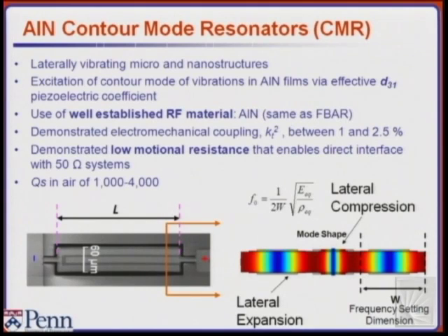And we solved one of the big problems generally associated with NEMS devices, which is the impedance matching. So we can design now a resonator with sub 50 ohm impedances, so we can directly interface it with electronics and so forth. And then we get Qs. The highest Qs are about 4,000. Of course, those are one of a kind. But generally, we get 1 to 2,000 for most of the devices that we make in air. Those are quality factors in air.